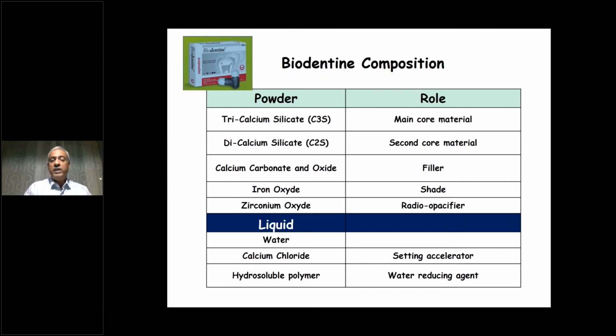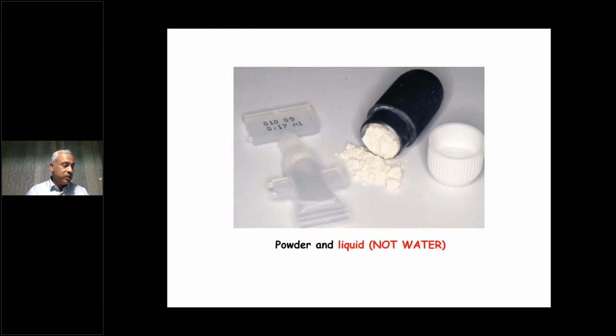On the other side, we have the liquid, and please note that the liquid is not water. It is a liquid because it contains some other components. So you cannot consider this as water because it contains calcium chloride as a setting accelerator. And if this material doesn't have calcium chloride, you'll need to ask the patient to keep the mouth open for 3 days, and he will not be happy about it. The other thing which is particular about this liquid is that there is a hydrosoluble polymer, and this allows reducing the amount of water that is incorporated into the material. And this is very important for obtaining good mechanical properties. So this is how the material is presented, a liquid and a powder. And again, please remember, it is a liquid and not water.